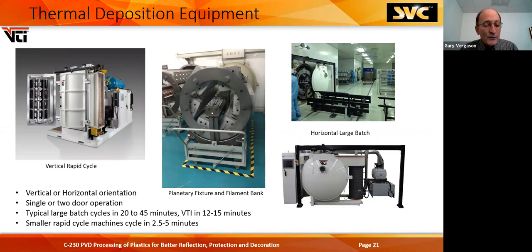You can have single or two-door operation. Usually these large batch coaters run in the neighborhood of 20 to 45 minutes. We put bigger pumps on smaller chambers, and this one that we have cycles 12 to 15 minutes.